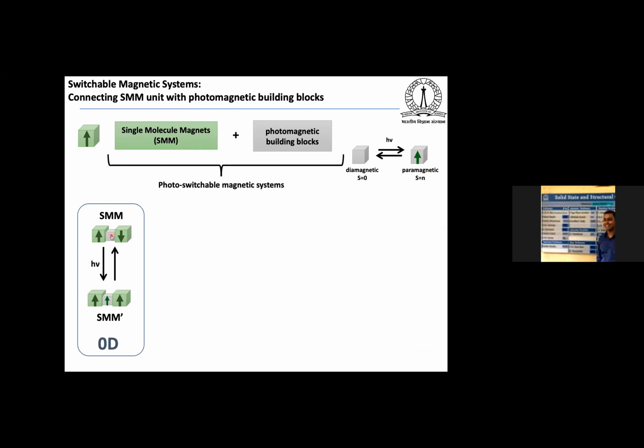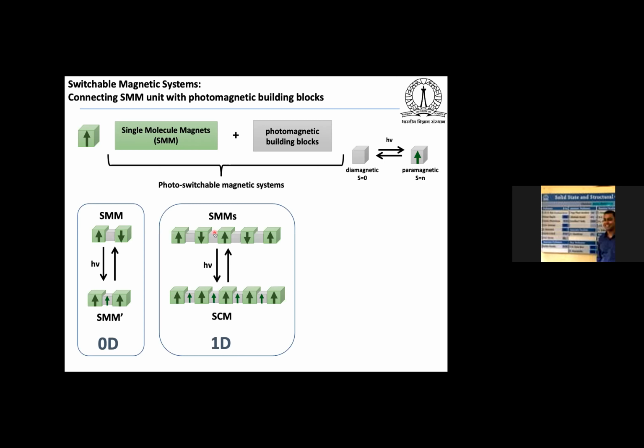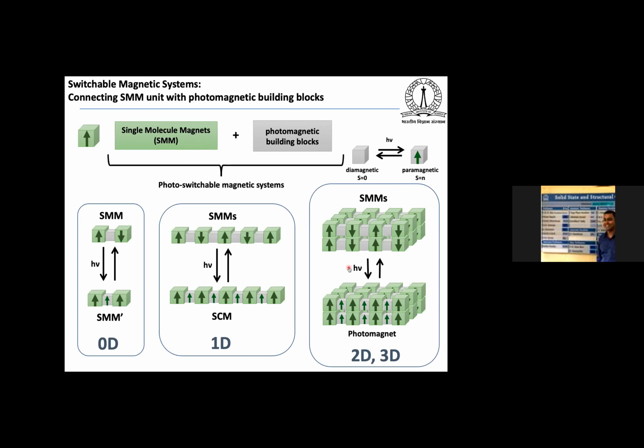So these linkers, before irradiation or below a certain temperature, will become diamagnetic. There will be no spin, and you can selectively generate the spin, and this will act as a different type of single molecule magnet. And then you can extend this network by using different linkers. We will get a single chain magnet under irradiation, and also you can link them in 2-dimensional and 3-dimensional, and you can get 2D or 3D photomagnetic systems where you can have the high DC of the system.